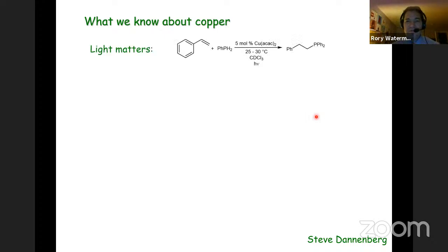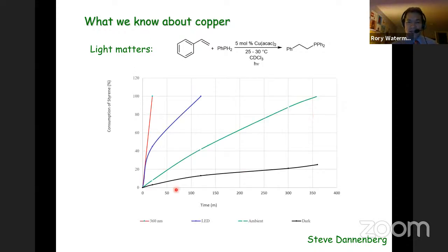And then further, the light obviously matters. So if we do this in the dark, we see considerably slower transformations. And I also show a light dependence here. So ambient lighting works quite well. So basically you can set this reaction up and run it. It just takes a bit of time to get full conversion. And so times in minutes, these are still not bad.